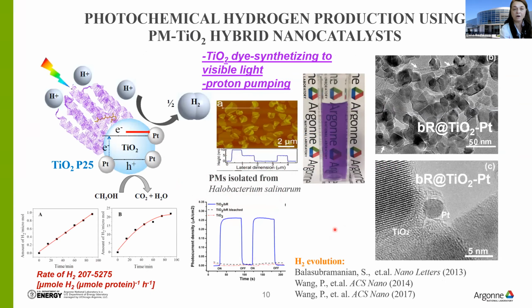So we started our works from photo-induced hydrogen generation, and we actually published a few papers about that with key ideas. If we mix titanium dioxide like P25 co-assembled with purple membrane, upon white light illumination, we observe hydrogen production. Using a variety of techniques, including photochemistry, transient absorption techniques and EPR, we demonstrated that in this system, biological material serves two functions. It's dye-sensitizing titanium dioxide to visible light, and it also enhances the water splitting reaction via proton pumping.